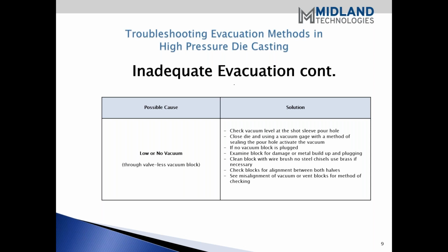As a general rule, this is just general. It doesn't mean that this is in every case, but we like to see vacuum levels between 13 and maybe 21, 22 inches of mercury. That should be sufficient. We've had some that go higher than that, obviously, and these are usually done with seals. You can utilize what's called, quote unquote, high vac or high vacuum die casting, which essentially means that you've sealed or minimized the amount of leakage in the tool itself, and those normally require some type of a seal.